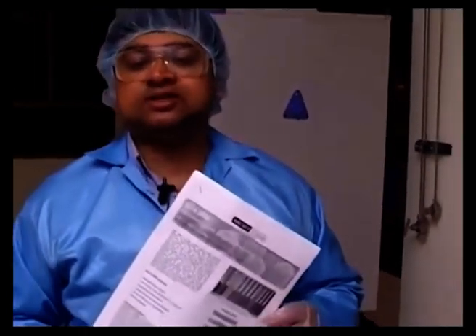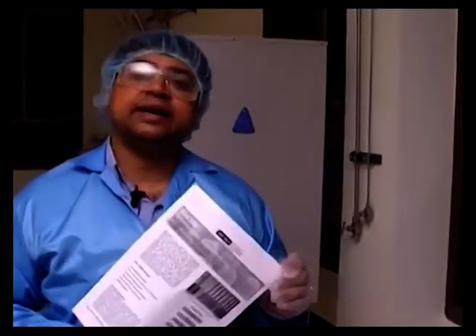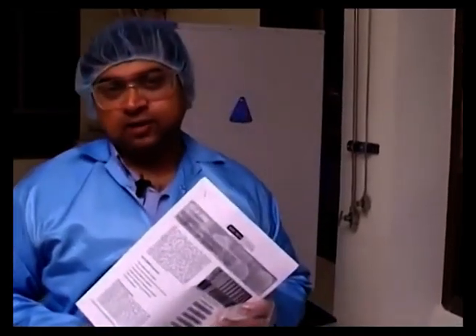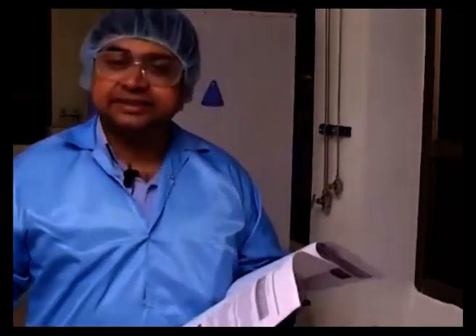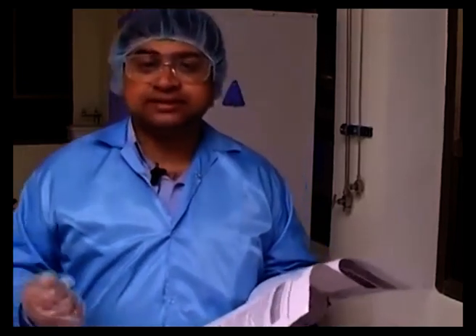So the first thing that is important here is to download the specifications of the particular grade of resist that you plan to use. What we normally do is use a resist from Microchem, a resist maker, and we are using a grade of resist called 2025 SU8, which has a certain viscosity. The resist manufacturer puts together experimental curves for this particular viscosity. What he determines is the RPM at which we should spin the resist so that a particular thickness can be achieved, and the thickness defined by the RPM is the thickness of the feature that we are looking at. It also mentions the temperature steps that you need to include